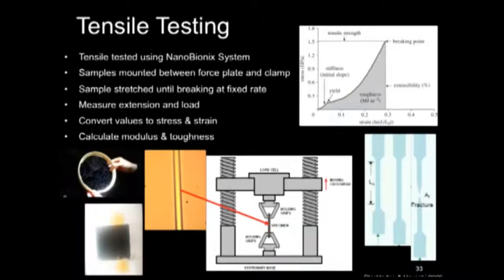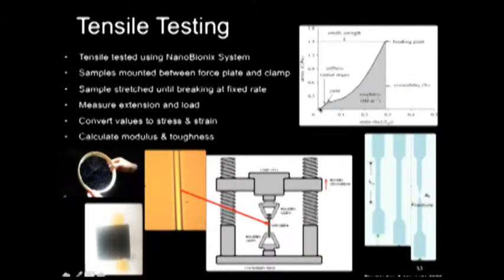So we use a very specialized machine called the NanoBionix System. We measure it by mounting the fibers between a clamp and a very sensitive force plate, and we stretch the fiber until breaking, and the point of fracture is what we measure as our ultimate stress and strain. These values allow us to calculate all of these variables, from the immediate measurements of extension and load converted to stress and strain, then calculating the modulus from the slope and toughness as the area underneath this curve, which is the overall work completed by the fiber, the energy absorbed by the fiber.